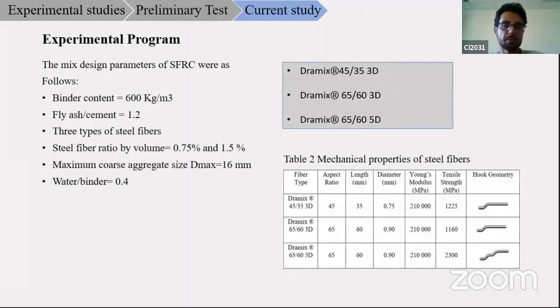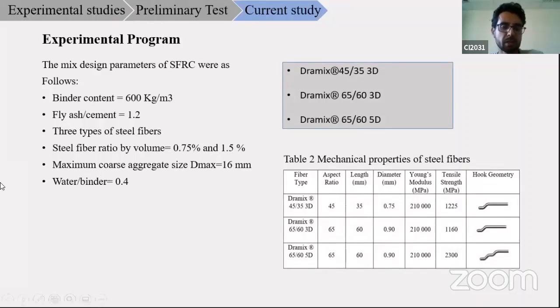Now I will present the current study. The mix design parameters are shown here. The binder content, the fly ash to cement ratio, is 1.2. Three types of steel fiber were used: Dramix with aspect ratio of 45 and a length of 35, 3D; Dramix with length of 60, 3D; and Dramix with length of 65, 5D. Here, the 3D represents one hook geometry, and the 5D represents the double hook geometry.